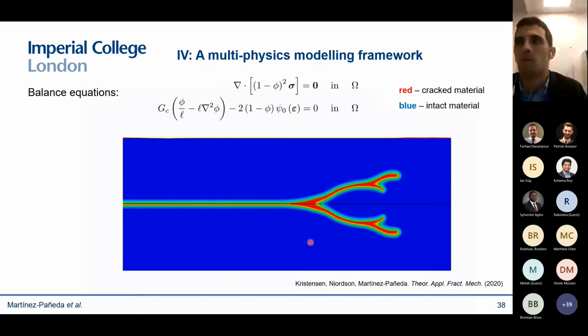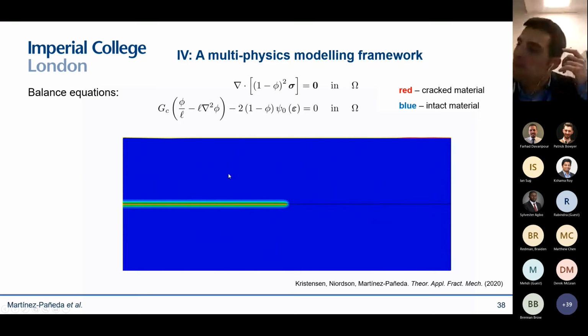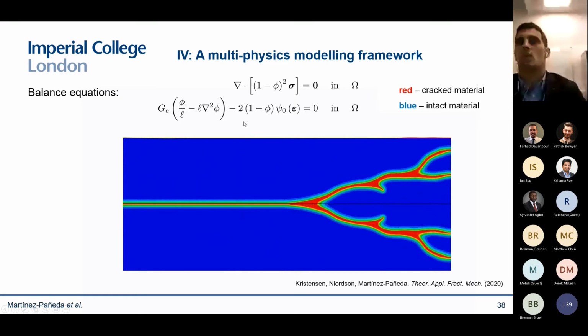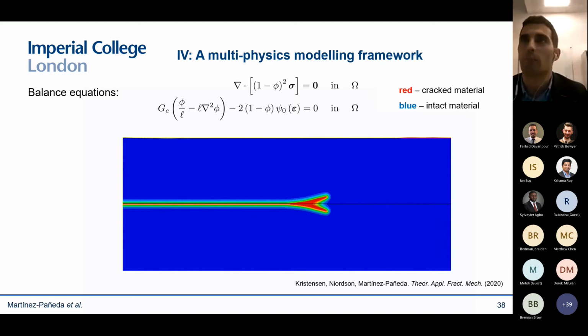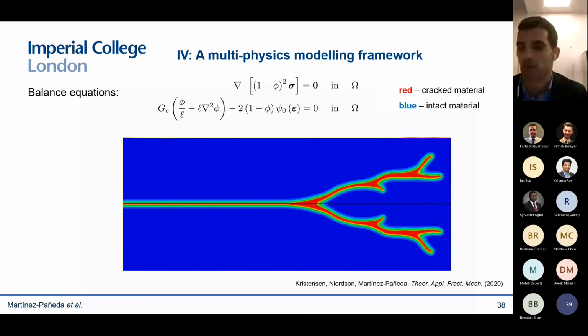You can see here an example where cracking is driven by the waves. This is dynamic loading, so that's why you see this funny cracking pattern. The red color denotes the cracks, by the way, and blue is intact material. And you can see that very complex cracking patterns can be solved just by solving this equation. So it's a very powerful method that is also physically sound. So it's quite convenient, and we have used this quite significantly.